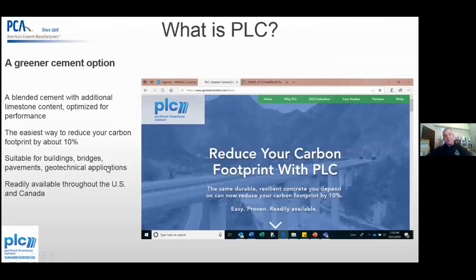So Portland limestone cements, it's a blended cement with additional limestone content up to 15%. So right now the Portland cement specs and the blended cement specs permit limestone up to 5%. But your Portland limestone cement is up to 15%. And it's a quick way to reduce the carbon footprint by 10%. It's suitable for buildings, bridges, pavements, geotechnical applications. And it is becoming more available throughout the US, and it is readily available coast to coast in Canada. It's almost the dominant cement in Canada. I think just this past year, it surpassed it. We don't have the statistics on it yet, but that's kind of where we're at.